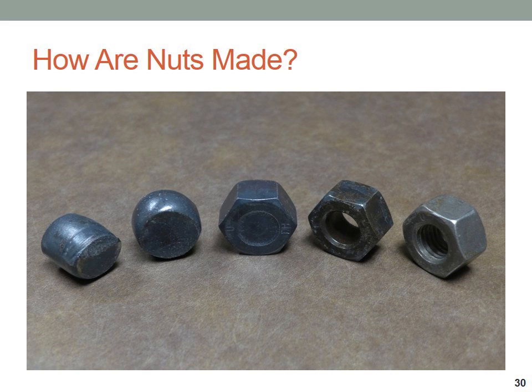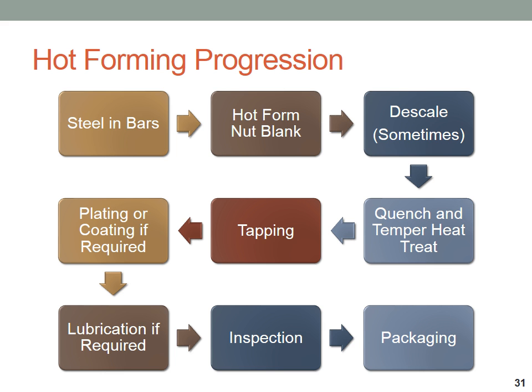Nuts are made. Here's a picture of a progression that shows nut forming. It's very similar. Typically in structural bolt sizes, all of the diameters of nuts would be what we call hot formed. Again, at very high temperature, where there's a cut-off blank, an upset, a partially formed hex shape, a pierced blank, and then a tapped final product with heat treatment, depending on the manufacturer, going on at different stages throughout that process. And again, the progression for hot forming is very similar to cold forming.